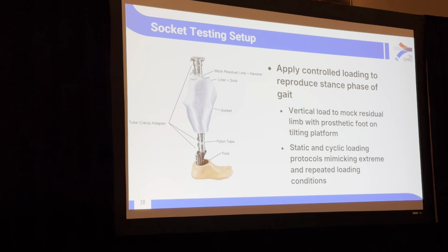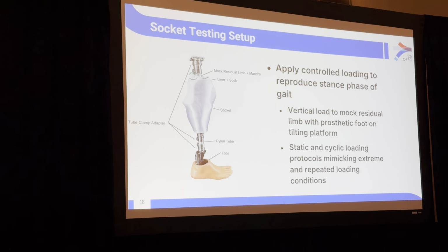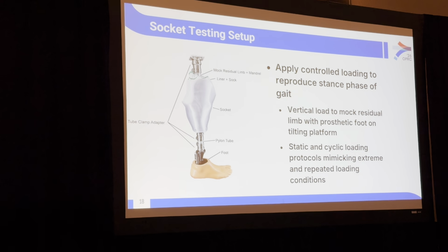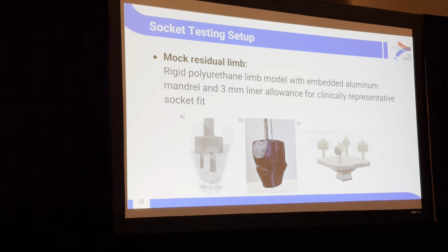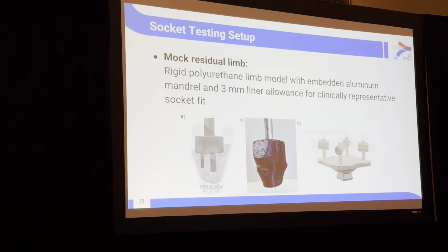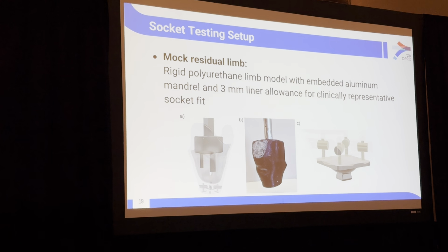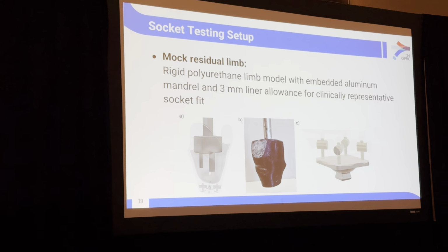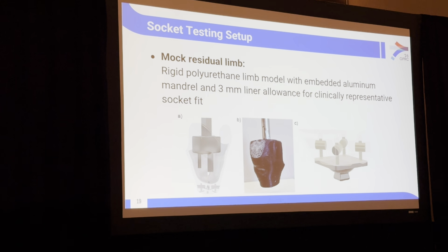This is a little bit of our socket testing sample, and so the mock residual limb had an embedded mandrel that allowed our socket sample to actually be mounted within the machine. For our mock residual limb, this was a rigid polyurethane limb model made with a 3D printed mold. There's an aluminum mandrel embedded within the limb model, and we also had a void 5 centimeters of the distal end in order to meet some of the requirements of the standard.